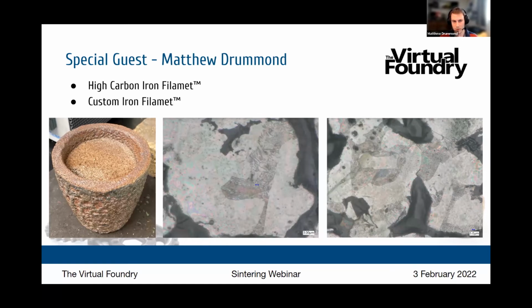And so something to combat that is to get a bigger crucible, put more sintering carbon in it, or we were even suggesting putting almost another crucible in behind it of just carbon. And that would allow the furnace and the oxygen in the furnace to essentially eat away at that carbon before it goes in and takes the carbon from your part. And so we're trying to keep as much carbon as possible within the part.